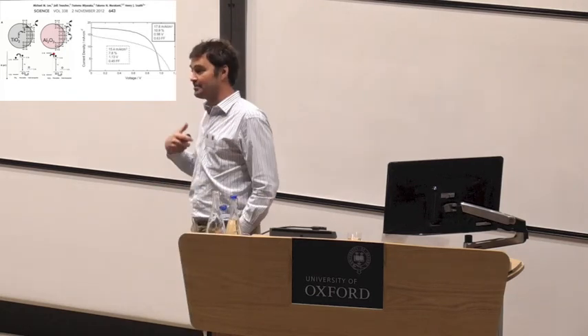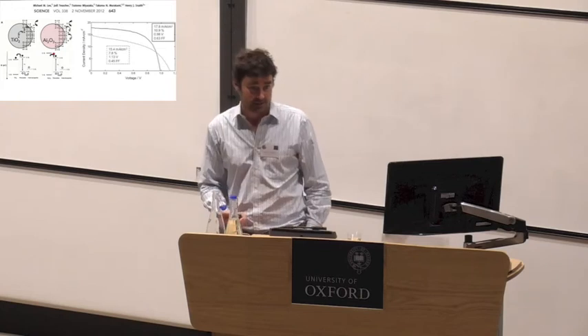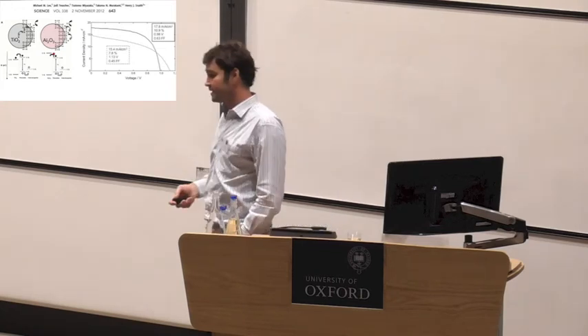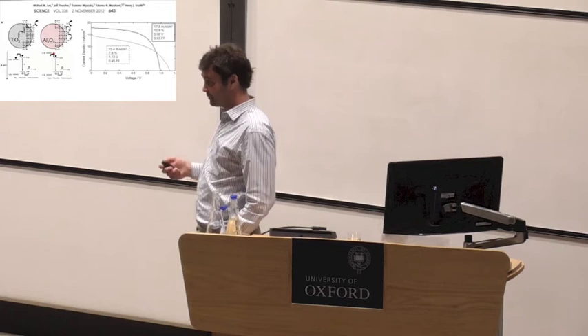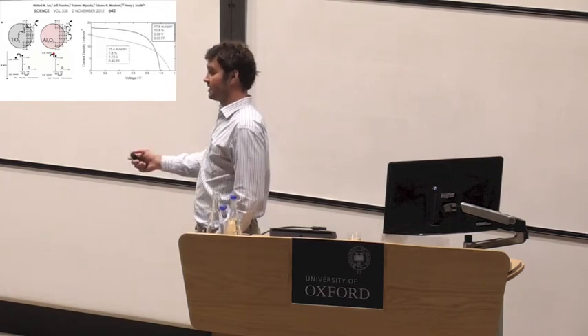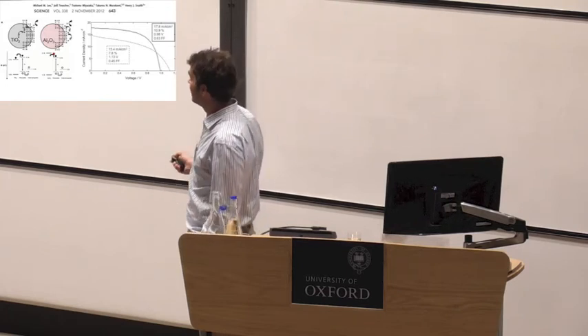And the voltage actually became much higher than the voltage you get for crystalline silicon, or indeed you would get for crystalline silicon if it was the same band gap absorbed in the same region. So it suddenly looked like it's a competitive technology. Of course, as well as voltage, we need to get current and fill factor.